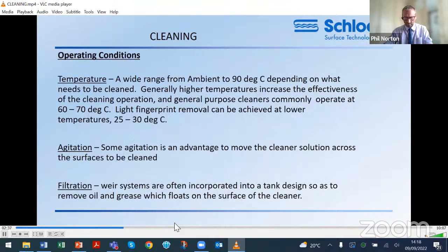Important aspects for effective cleaning include temperature. This can be anywhere from ambient to 90 degrees centigrade depending on what needs to be cleaned. Generally, higher temperatures increase the effectiveness of the cleaning operation, and general purpose cleaners commonly operate at 60 to 70 degrees centigrade. However, light fingerprint removal can be achieved at lower temperatures, for example 25 to 30 degrees centigrade.